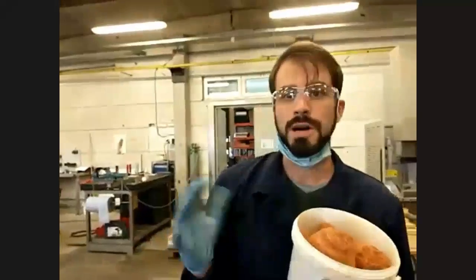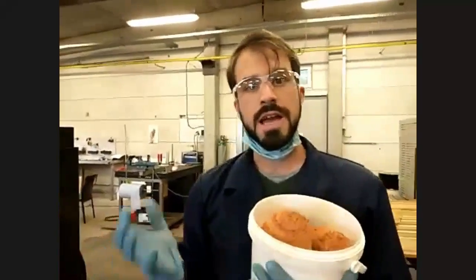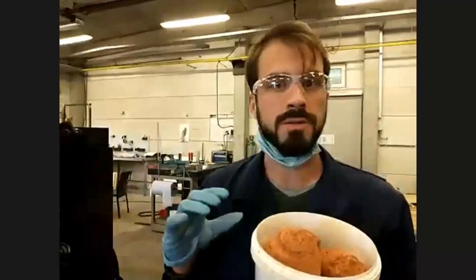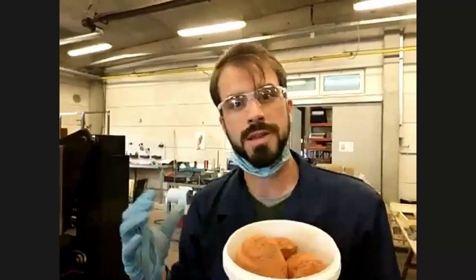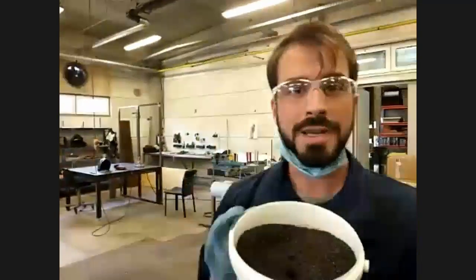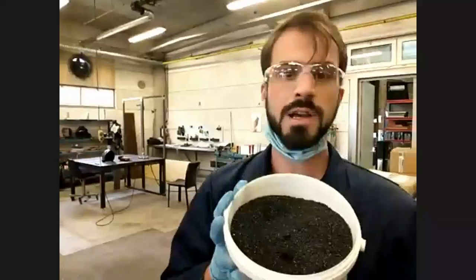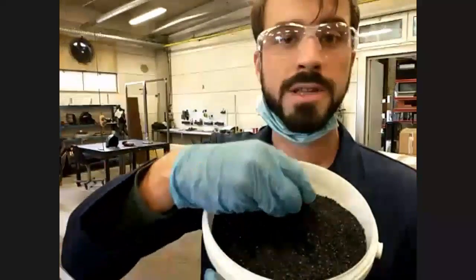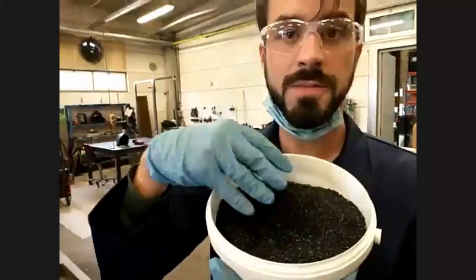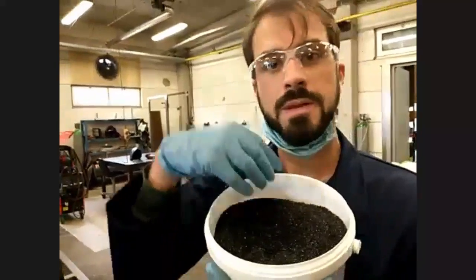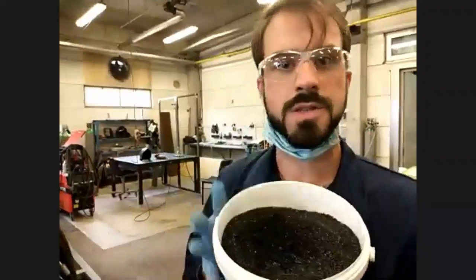And as mentioned, we go to temperatures around 1200 degrees where we partially melt or sinter this material. And the next step is to quench this material very fast. So basically, we want to transform the melt that we form in the furnace into something glassy that is reactive as a binder material. When we quench that material, what we basically get out of the furnace looks a bit like this. So we have a slag material, which you can see also has changed the color. That depends on the certain additives that we mix with the bauxite residue in the previous containers.